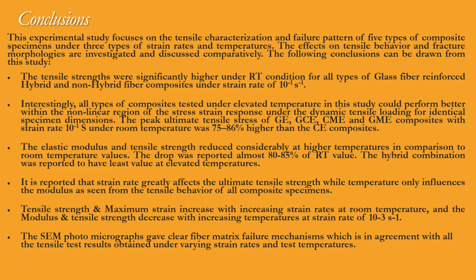Interestingly, all types of composites tested under elevated temperature in this study could perform better within the nonlinear region of the stress-strain response under the dynamic tensile loading for identical specimen dimensions. The peak ultimate tensile stress of GE, GCE, CME and GME composites with strain rate of 10^-1 per second under room temperature was 75 to 86% higher than the CE composites.